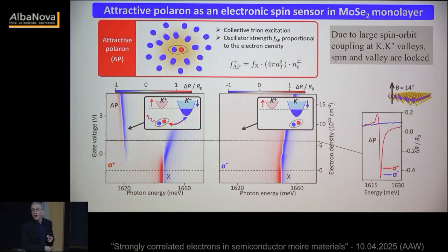So how do I see this? We go to very large magnetic fields. At these large magnetic fields, we inject electrons and they remain valley polarized because the g-factor is something like 4, which means that up to about 10 to the 12, all my electrons will go to the K minus valley. Now, if I inject my exciton in K plus valley with sigma plus light, I see this nice attractive polaron and the repulsive polaron formation. But if I use sigma minus light, then I see my exciton that is still blue shifting.